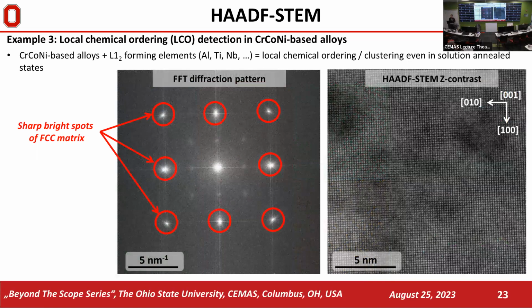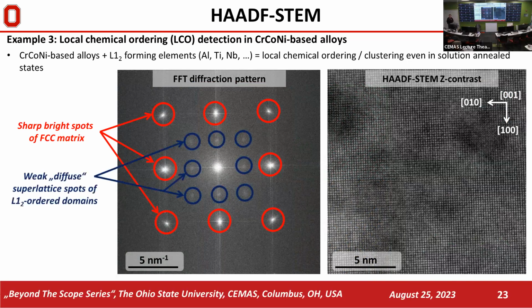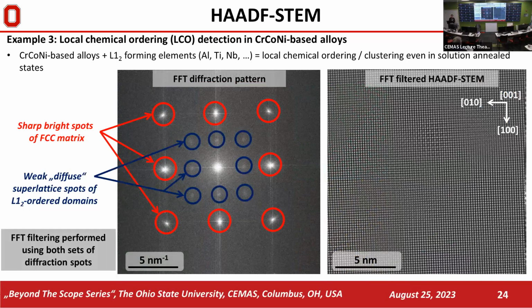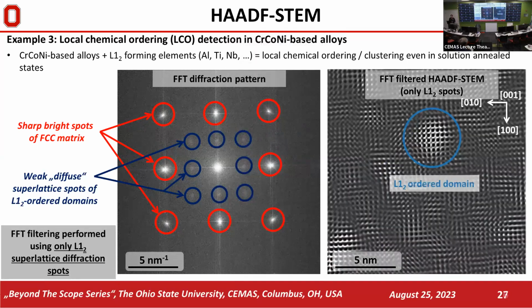If you just simply do an FFT diffraction pattern of your atomic resolution data, you can see the diffuse superlattice spots related to L1_2 ordered domains very nicely. You can go further and use FFT filtering, either using all the spots from both phases, or you can just do an inverse Fourier transformation using just superlattice diffraction spots and visualize these ordered domains, which are about 3 nanometers in size. So this is another use of high-angle STEM to deliver important information, important answers for questions and topics which are being studied now in structural materials.